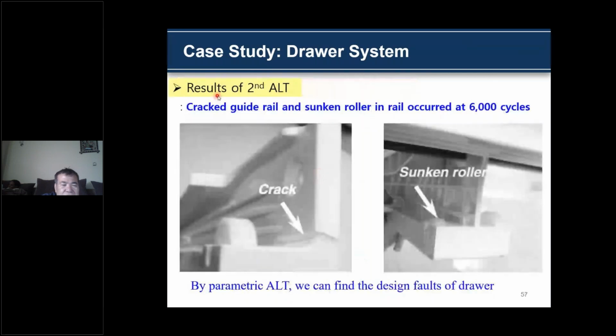This is the second parametric ALT result. We found a cracked guide rail, and then also sunk the roller at 6000 cycle. By parametric ALT, we can find a design faults of the drawer system.